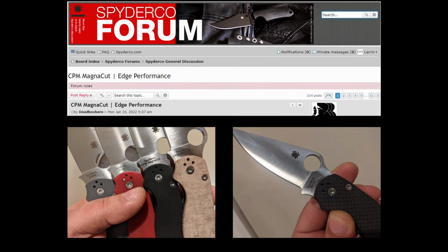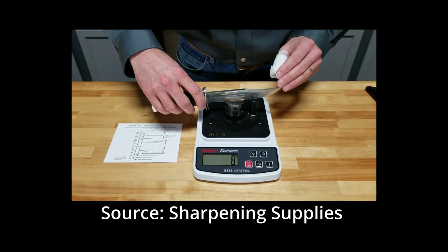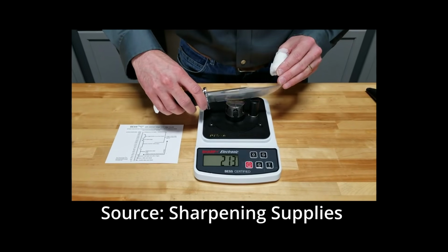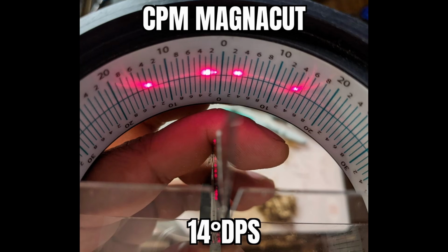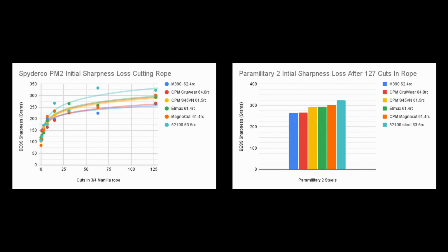He used several Spyderco PM2s in different steels and measured the change in BESS sharpness with cuts in 3/4 inch manila rope. Each knife was sharpened to 14 degrees per side using a fixed angle sharpening system and tested at different points on the way to a total of 127 cuts. The MagnaCut PM2 here is a prototype and is not available for purchase.